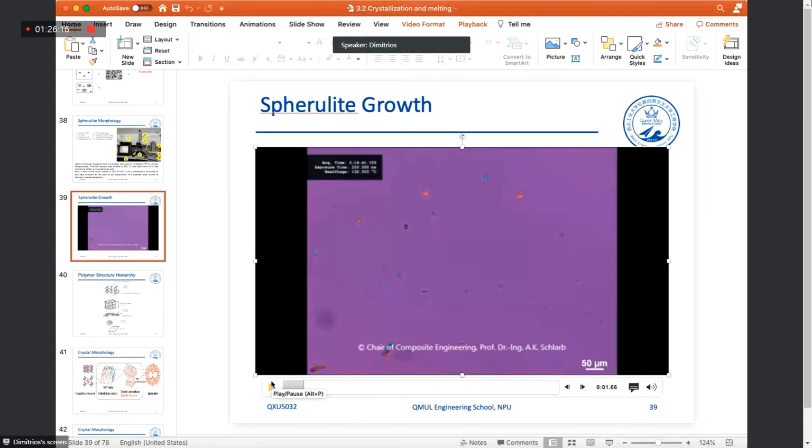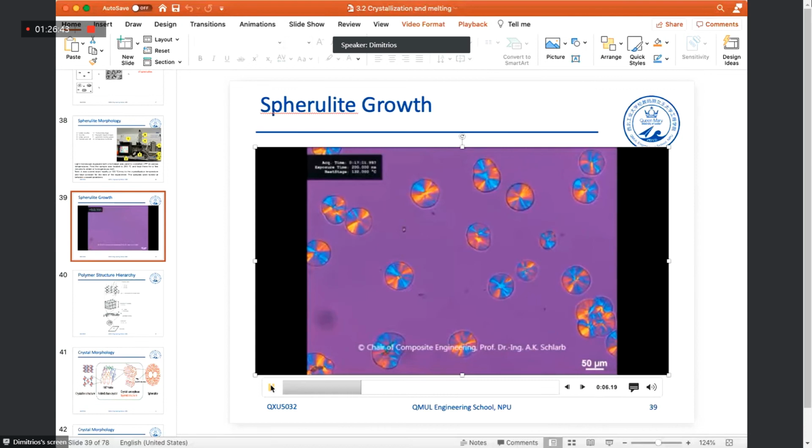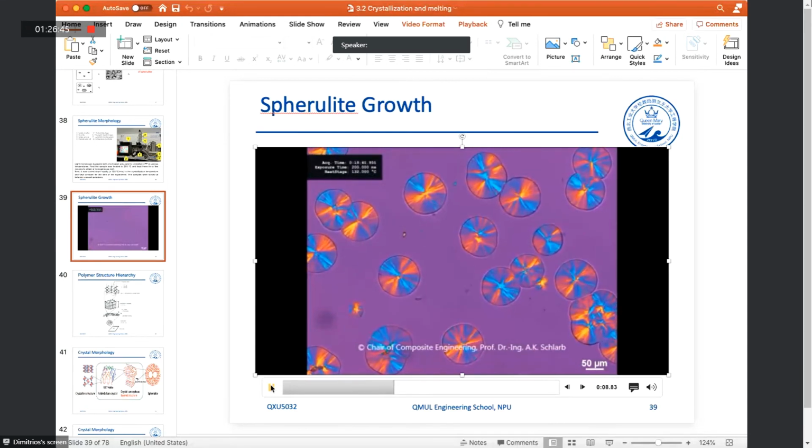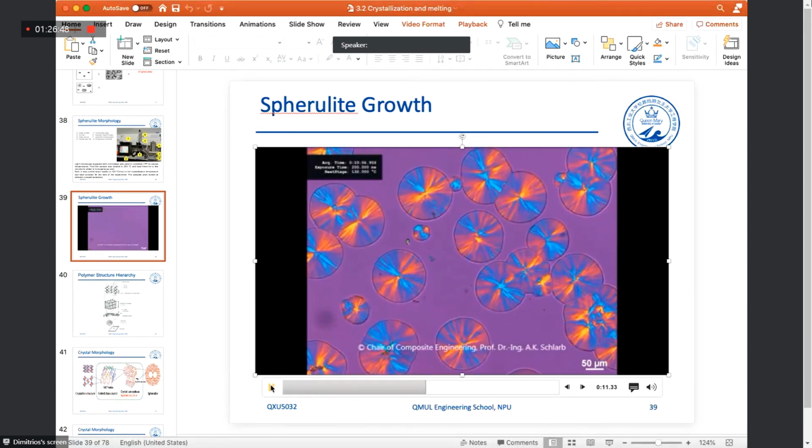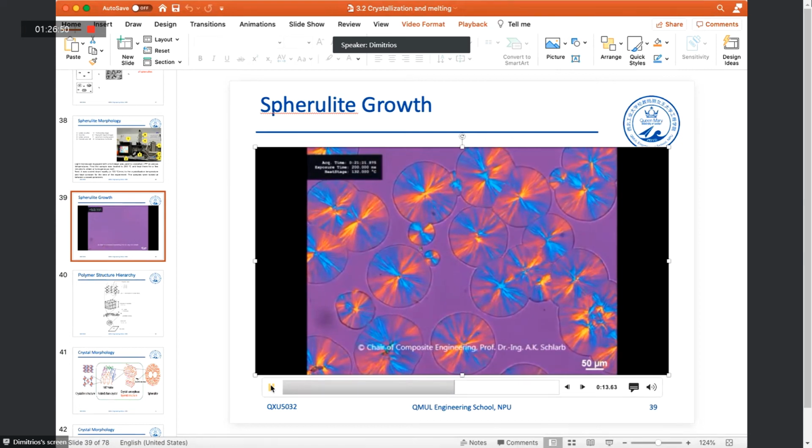The only thing we can control, and it is important to try that in the preparation process when we have nucleating agents, these foreign particles that I was saying, such as fillers, pigments, and so on, is to make an attempt to essentially disperse them as much as we can within the melt. Okay, that is during the preparation process. So you can see that the spherulites grow with each other until we observe impingement.